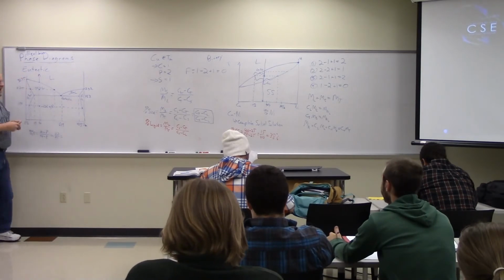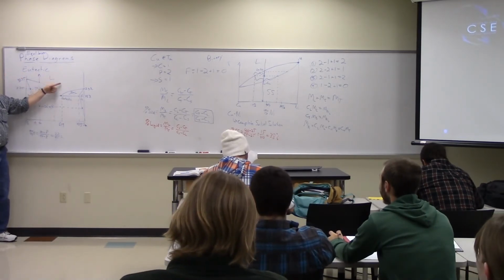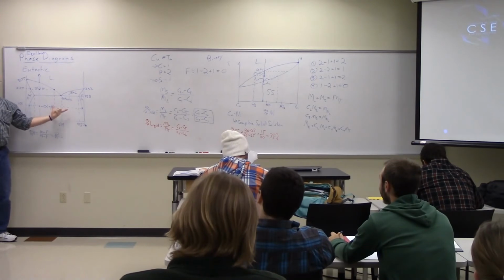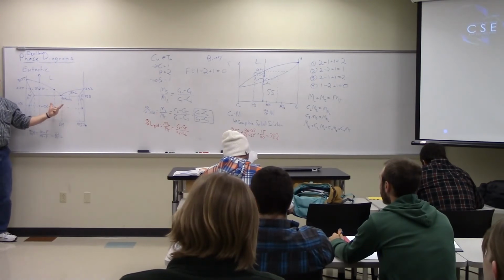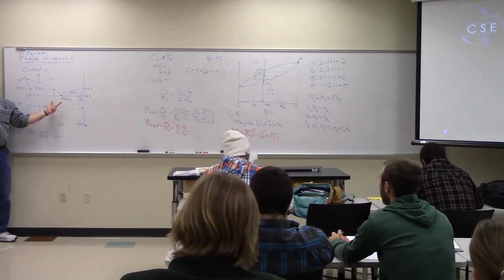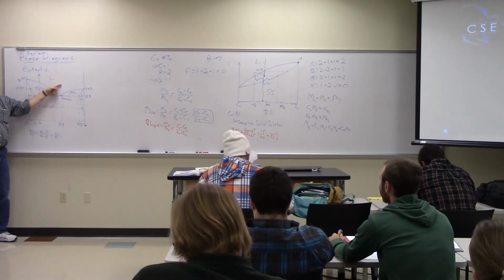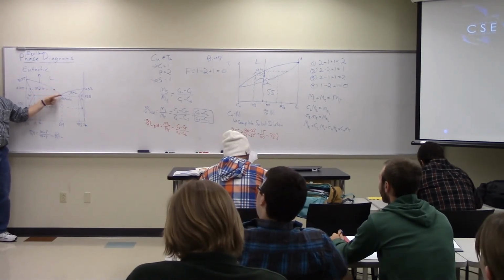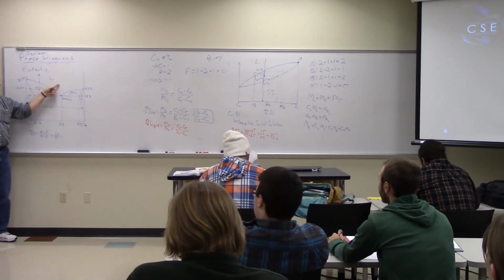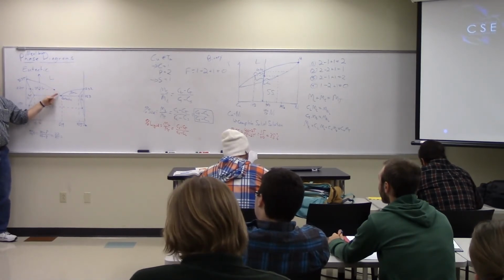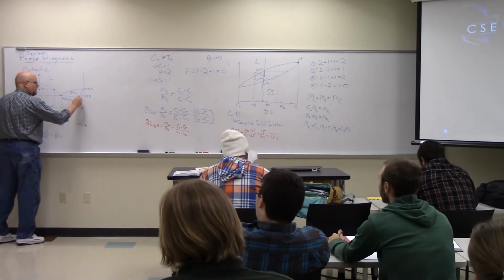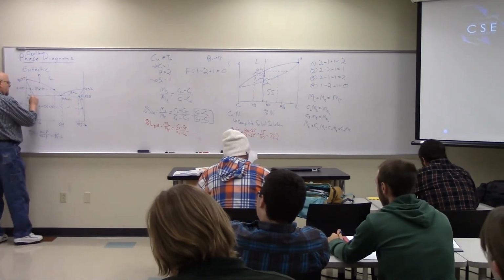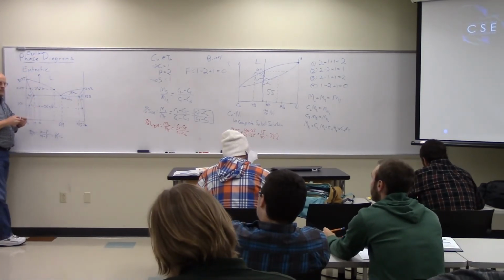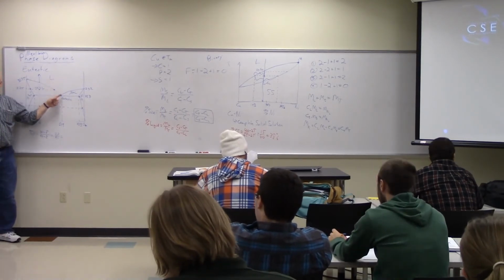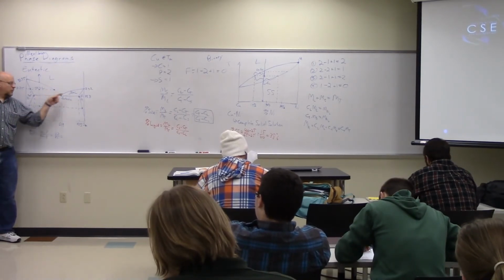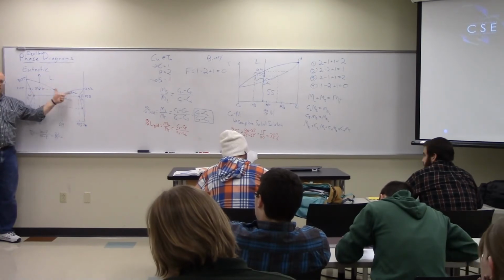That is the point where there's an eutectic conversion from liquid to a mixture of solid solutions. It means it all happens at once. As I cool down through this point, I don't go through a mixture of liquid and solid. I go right from liquid to solid. And the solid that forms is a mixture of that composition of beta and this composition of alpha. So in an instant, I have this uniform liquid, and as it cools, it forms a mixture of two solids that are distinctively different solids.